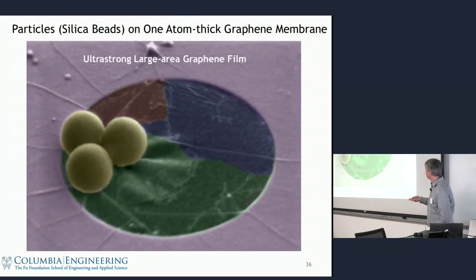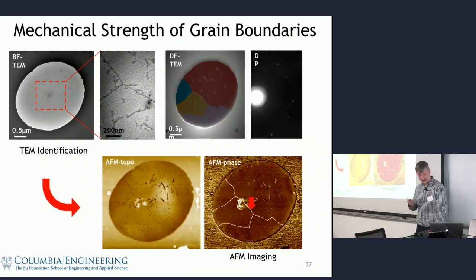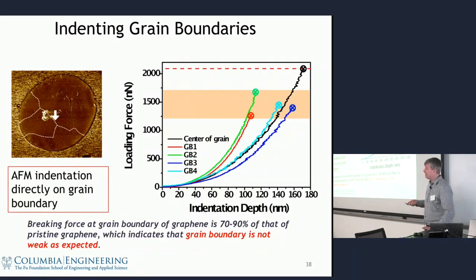And we demonstrated this. You can put some little beads on here, and this graphene membrane supports it. And we also did nanoindentation testing on single grain boundaries. So we took grain boundaries, mapped them in TEM, then took them to the AFM and found the same grain boundary and did nanoindentation tests on those. And again, we saw that the loading force was lower on the grain boundary, but not dramatically so, a factor of 30% or something like that.